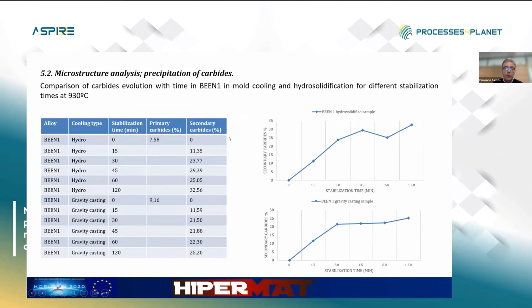If we take it into numbers by making an image analysis, we can see that the percentage of primary carbides is higher in the case of gravity casting, whereas the percentage of secondary carbides is significantly higher in the case of, let's say, hydrosolidified samples. We can see the graphs.